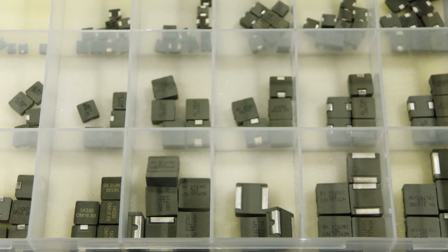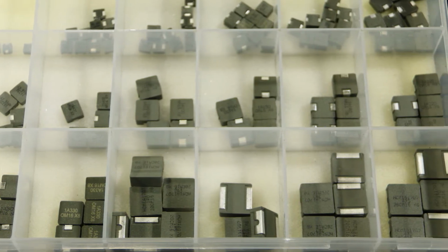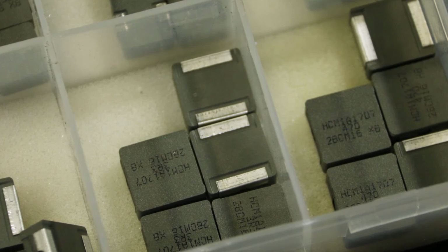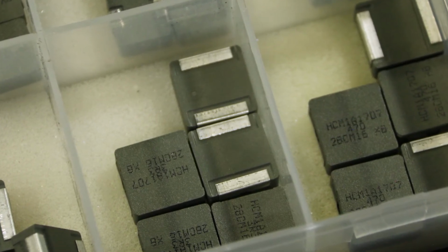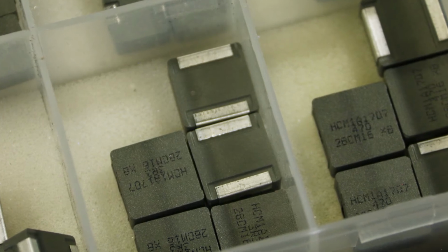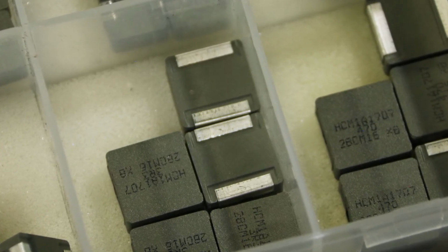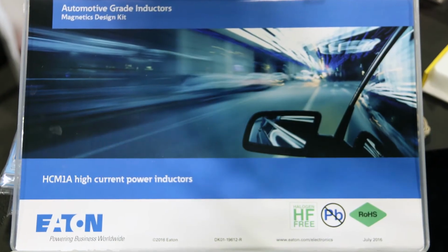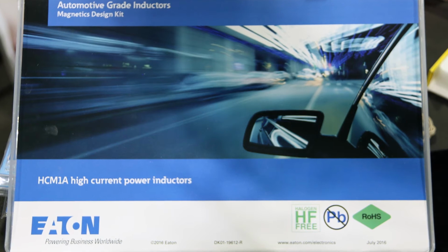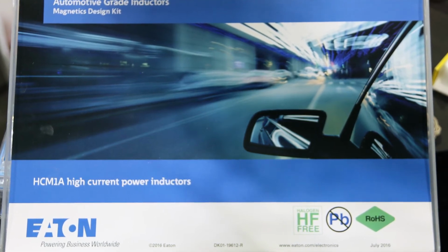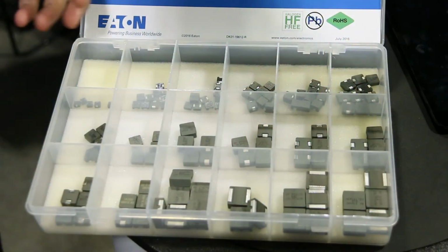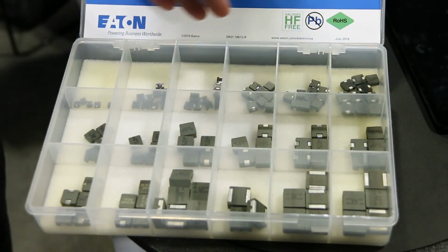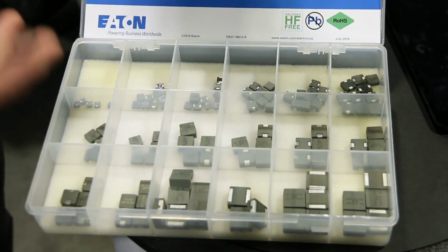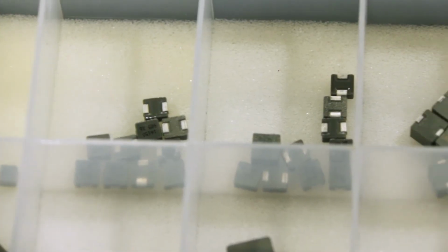Some of them are in what we call the ferrite category. What it means is you will have different types of ferrite combinations on the cores, but it will also need a discrete gap to allow you to perform at a certain current. The other category will be when you have materials like pressed powder inductors, where you can achieve a distributed gap. The beautiful thing about pressed powder, powder iron inductors, is that the distributed gap would allow you to achieve the highest amount of inductance at any given high current level. While with ferrites, once you're getting into a higher current level, and depending on the temperature, you can start seeing a roll-off.